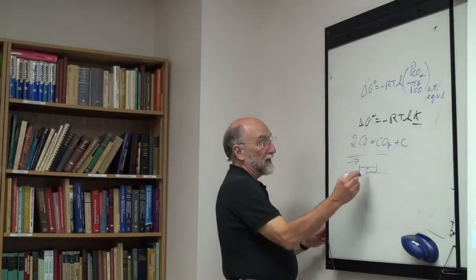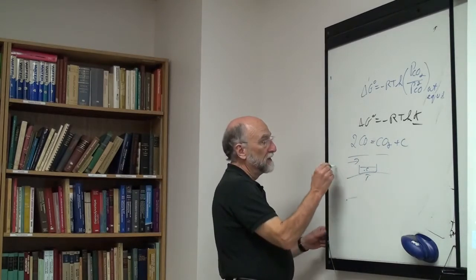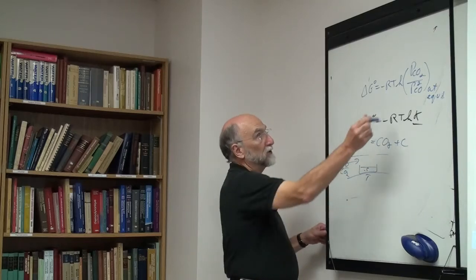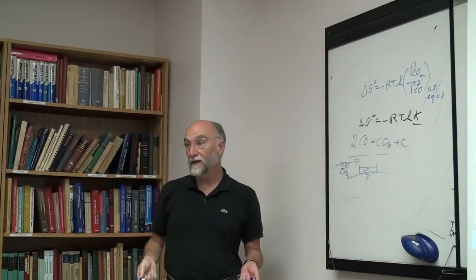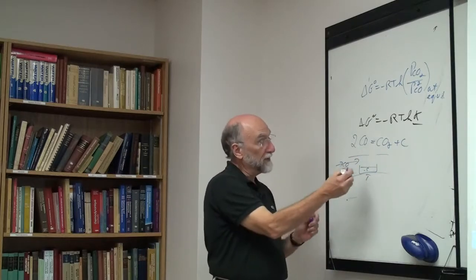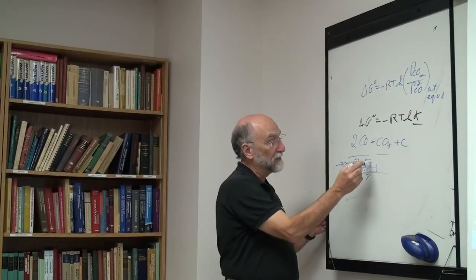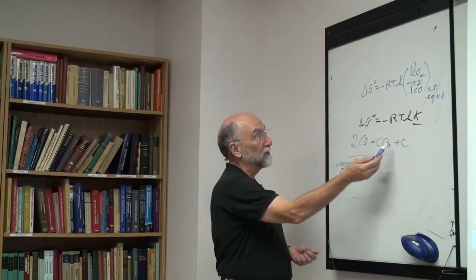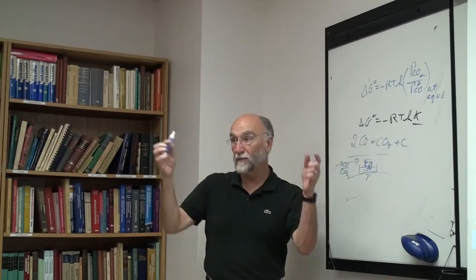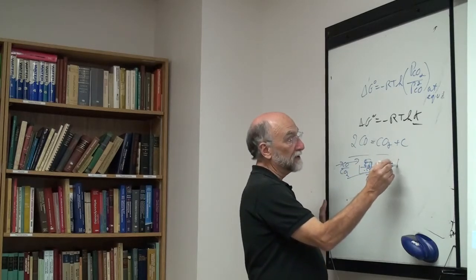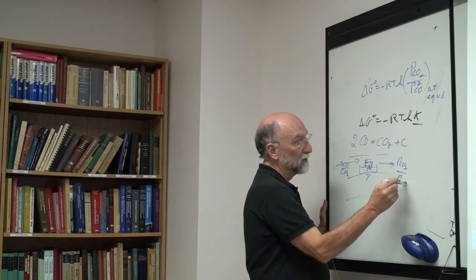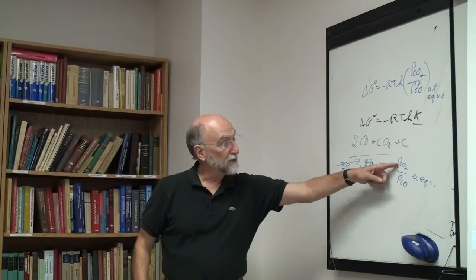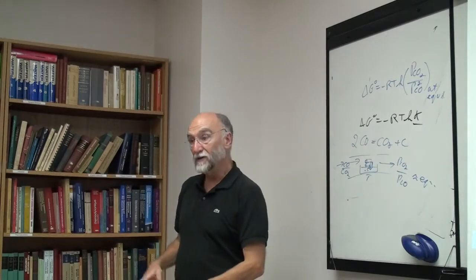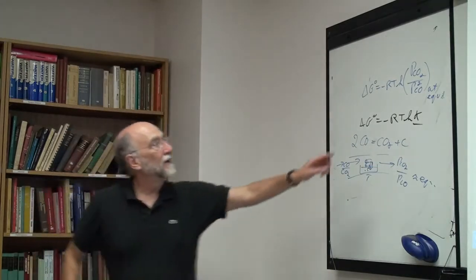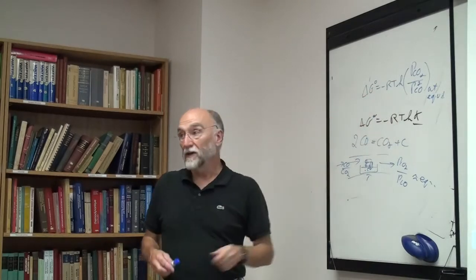So I put in my furnace at a temperature T some carbon. Here I pass a mixture of CO and CO2, which is approximately equal to the ratio I expect at equilibrium. The gas equilibrates. You pass it slowly at temperature here, then equilibrium is established. Either carbon reacts with the CO2 or some CO2 deposits carbon. And then at the exit, I assume that PCO and PCO2 are approximately their equilibrium values. So I measure PCO2 and PCO at the output, either by spectroscopy or some other method. And then I have the two partial pressures, I put them in here and I get delta G0.